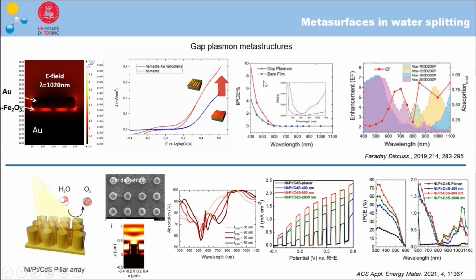A similar effect also happens in this second example. In this case, we create a self-standing photoanode made of nickel nanopillars covered with platinum to give more robustness in terms of chemical stability, and a cadmium sulfide semiconductor which drives the oxidation. Also in this case, as you can see, we can obtain broadband absorption and a very high increase in photocurrent. We can triple the photocurrent if we compare the planar films with the one made of nanopillars.